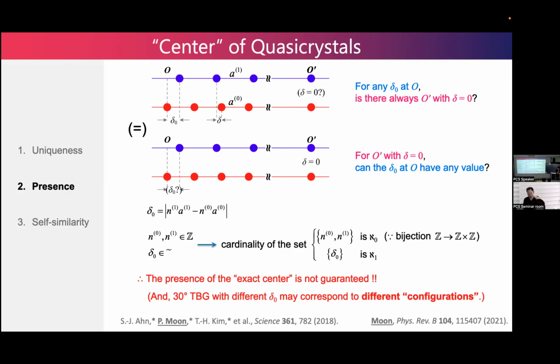So in graphene, even though you said that this is equivalent, maybe, but it's the quantum theory. You can always find the same structure with a very small picometer error or something like that. So we are sure that the shear point should be zero. However, if your argument seems to be very nice, can you think of some material where, depending on the quasicrystalline order, there is a difference in the shear point?